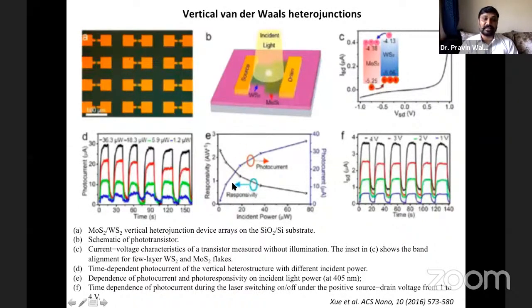Here in another figure, you can easily see the responsivity with respect to the incident power. The responsivity decreases if you increase the incident power, but at the same time, the generation of photocurrent is quite good as you increase the incident power, right? So this is the characteristic of the photodetector if you have the vertical junction of WS2 and MoS2. But what is the role of the gate voltage? Here you see, if you increase the gate voltage from 1 to 4 volts, the photocurrent generation is improved and the response time is almost the same, right? The only thing is the on-off ratio, so the responsivity is very high, right? So the gain of that particular photodetector would be very nice.